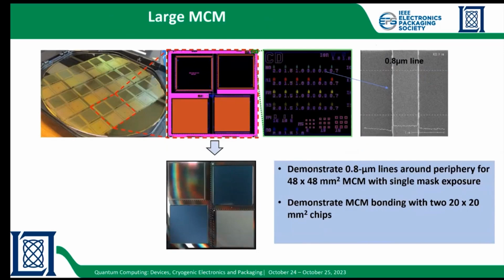So this slide will answer our first question. The first question was, what would be the largest MCM we can build using a single I-line mask exposure? For I-line mask, the largest print will be around 52 by 52 millimeter. To avoid any lens edge degradation, we select 48 millimeter by 48 millimeter field size as our largest MCM, which can print 0.8 micron wide 50 ohm lines across the MCM for chip-to-chip communication.